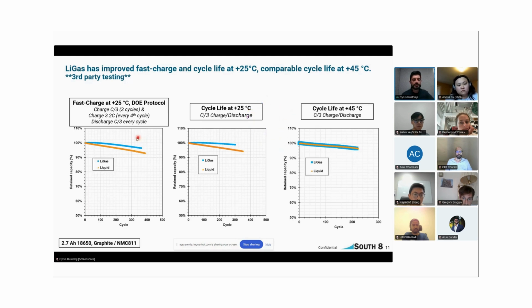And you can actually see that the gas cell is outperforming the liquid cell. We believe this is primarily due to the improved conductivity and the lower SEI impedance we have on the anode. So that allows less lithium plating on that anode and faster diffusion into the anode during these fast charge protocols. So we all know during fast charge, it's really the lithium plating that will kill you and kill your cycle life. So we actually mitigate that with the lower impedance SEI layer on that cell.